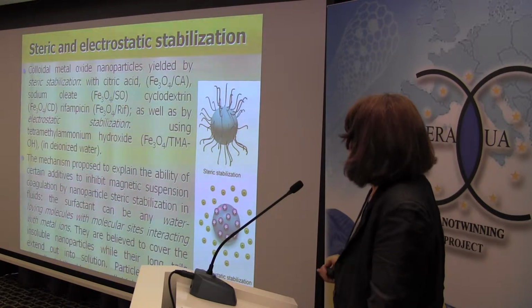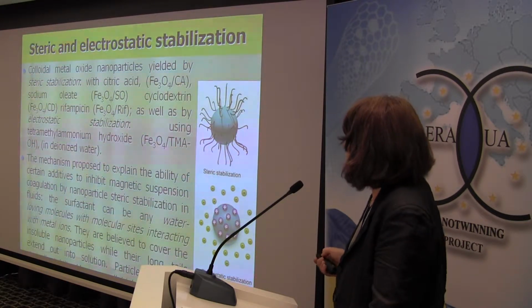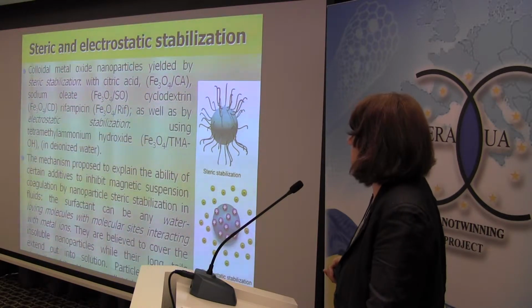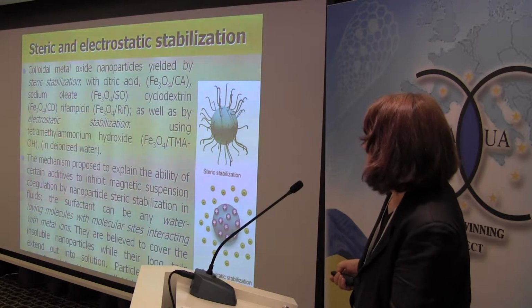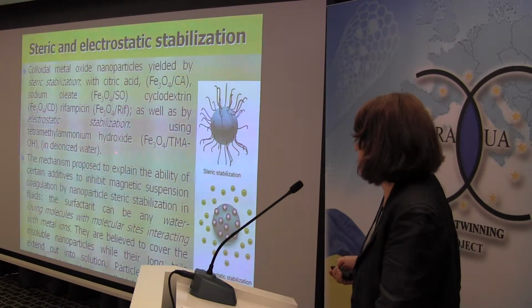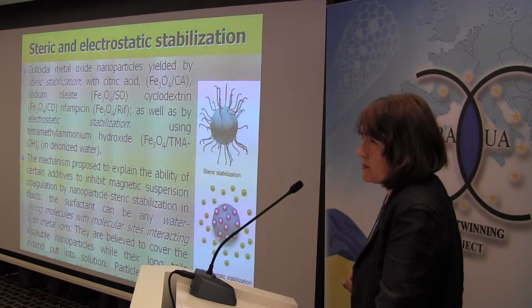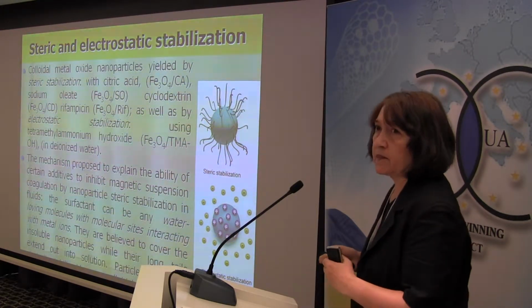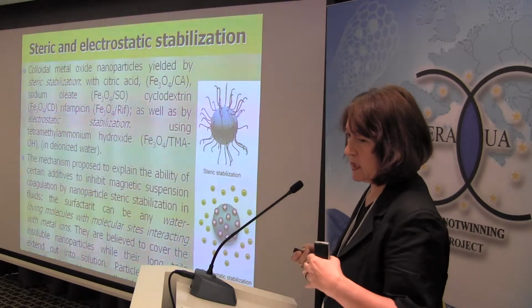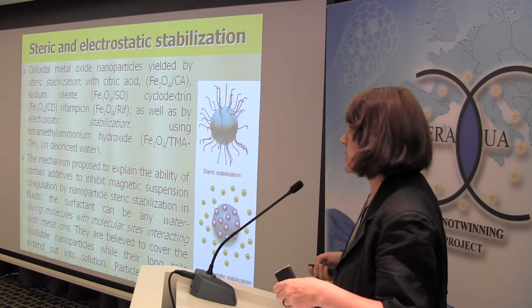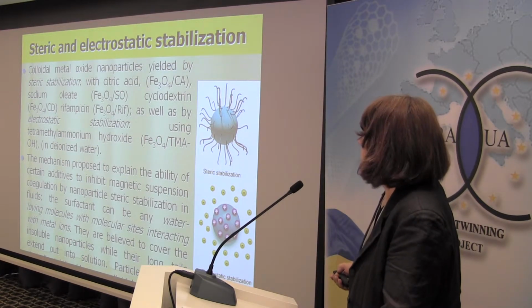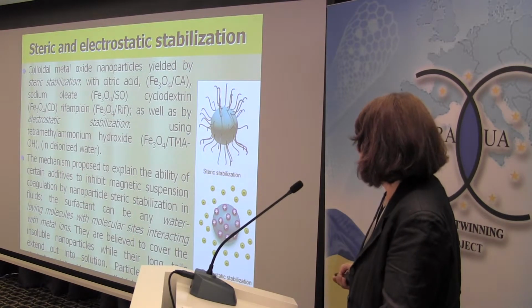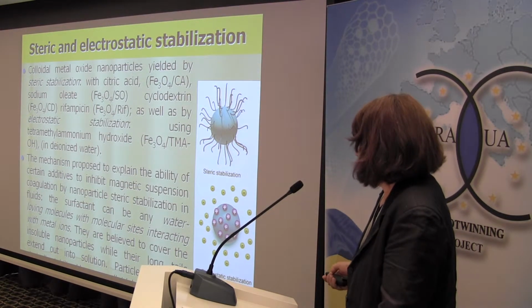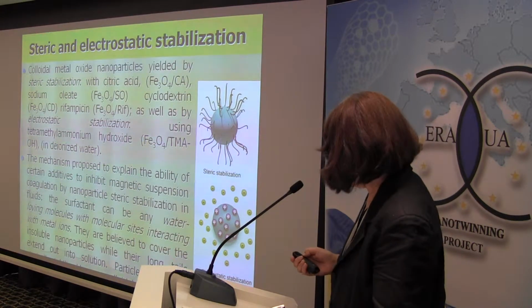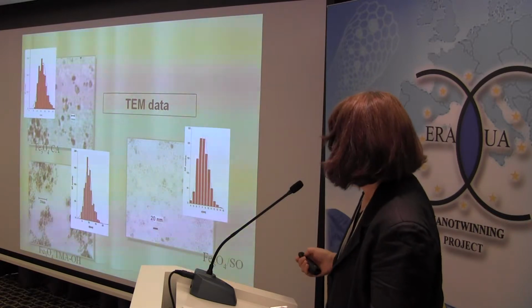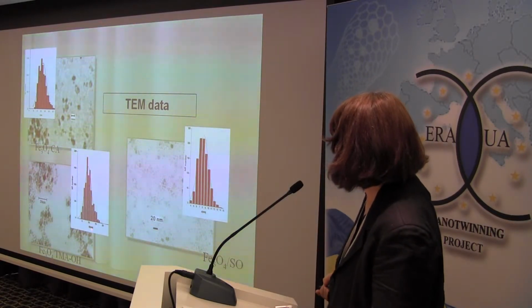Here are some considerations regarding the two types of stabilization of nanoparticles within the carrier fluid. Except the tetramethylammonium hydroxide, where electrostatic stabilization is the main physical process, ensuring the repulsive forces among colloidal particles, able to balance the attraction forces between magnetic dipole-dipole. In all other cases, there is a steric stabilization with the water-loving molecules with molecular sites able to receive cations from magnetic nanoparticles. Here are the transmission electron microscopy data and histograms.